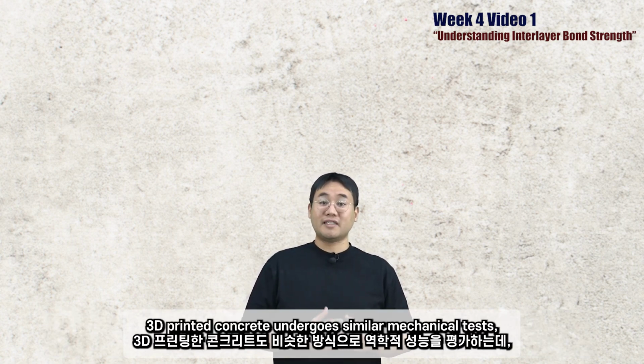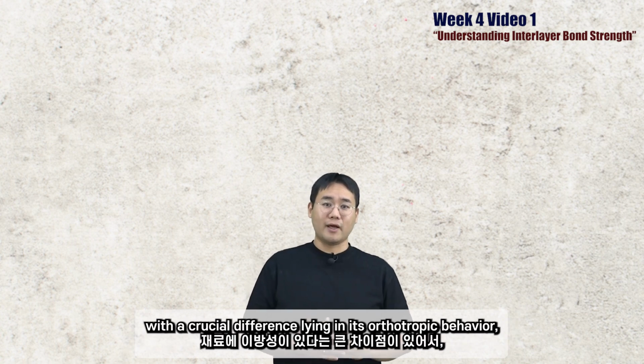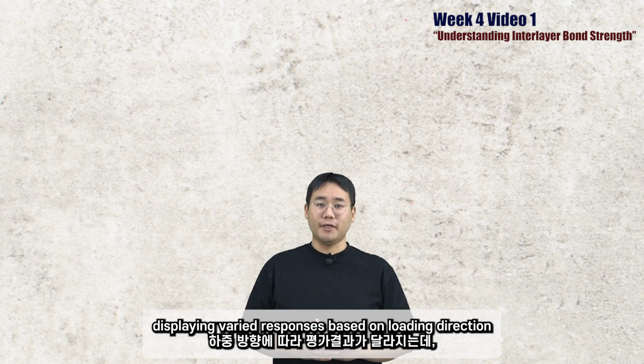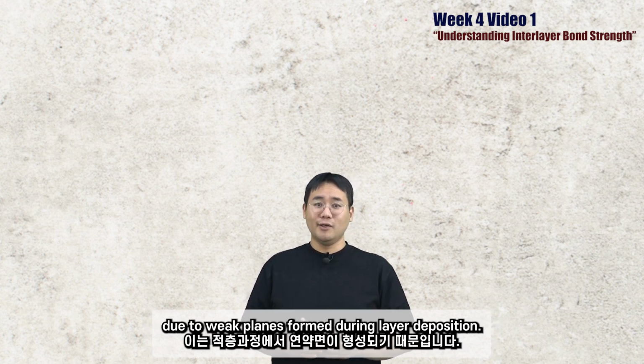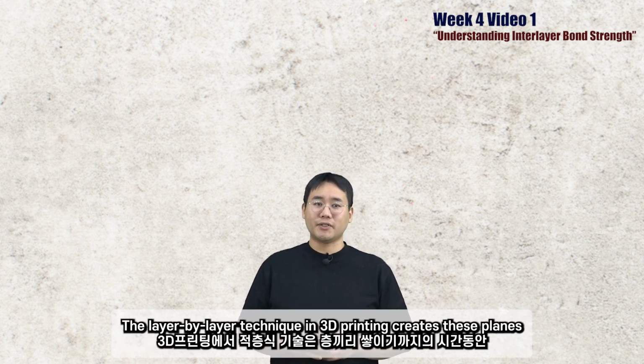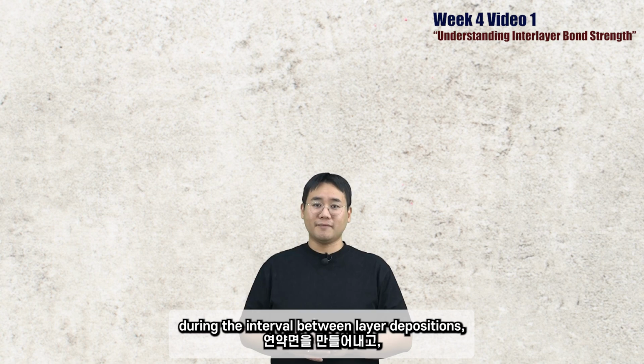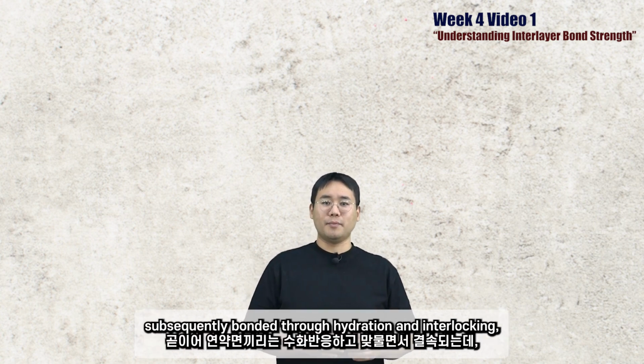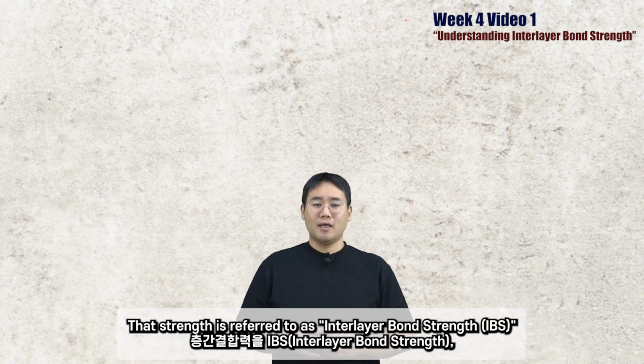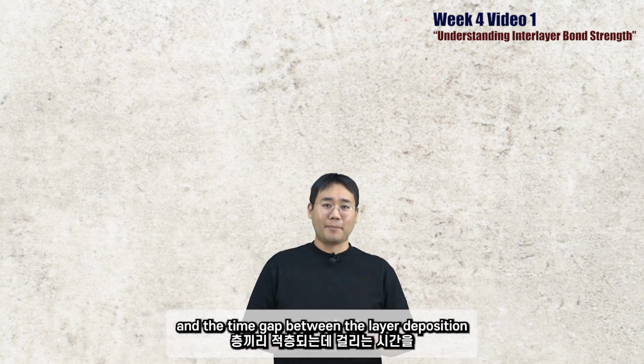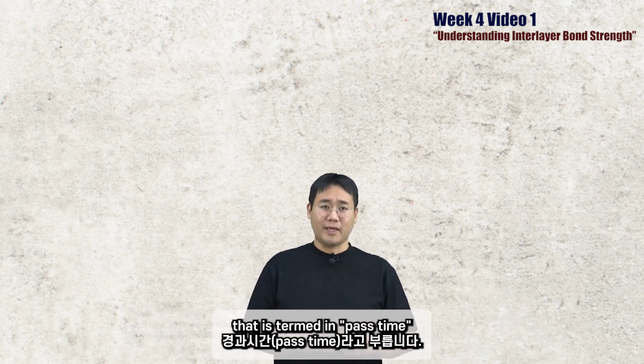3D printed concrete undergoes similar mechanical tests, with a crucial difference lying in its orthotropic behavior, displaying varied responses based on loading direction due to weak planes formed during layer deposition. The layer-by-layer technique in 3D printing creates these planes during the interval between the layer depositions, subsequently bonded through hydration and interlocking. That strength is referred to as interlayer bond strength, sometimes shortened to IBS, and the time gap between the layer deposition is termed pause time.